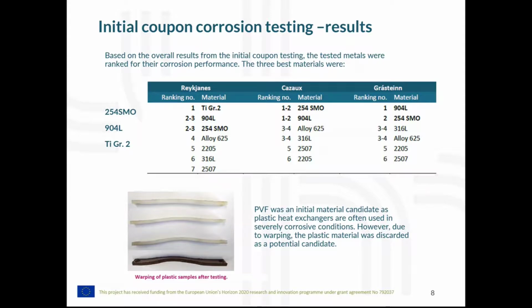the heat exchanger plates. And as a side note, as I mentioned earlier, we did test some plastic PVF since plastic heat exchangers are used in highly corrosive conditions, specifically in chemical processing, and we decided that it might be interesting to see if it could prove a candidate for geothermal heat exchangers. But as it turns out, the plastic warped quite a bit, both at Cazaux and Grásteinn, so it was discarded as a potential candidate.